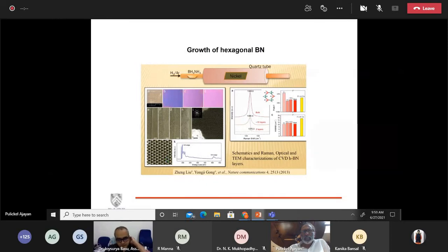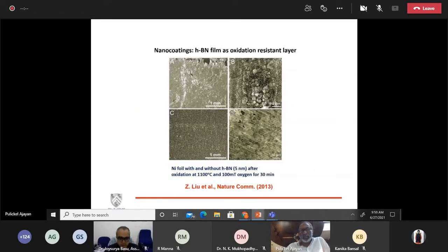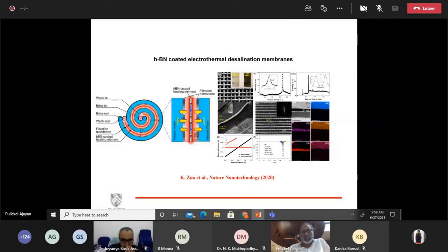Well, hexagonal boron nitride itself is a very fascinating material. It's similar to graphene, but it's very robust in terms of oxidation resistance. We have shown that these layers, a few layer thick BN, can be extremely good in oxidation resistance at very, very high temperatures. Recently, we have also shown that if you coat this boron nitride on some of these steel meshes, which are used in desalination membranes, they can be protective in terms of the metal not being oxidized, and that allows industrial performance to be much better. It's actually a very recent paper that shows that BN can be very useful.